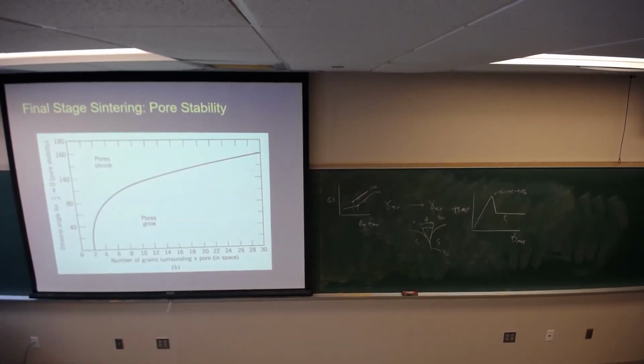One more comment though. Your dihedral angle is fixed because it's dictated by the ratio of gamma SV to gamma SS. So you have a constant dihedral angle, and if on this plot you drew a horizontal line, that would tell you then, based on that dihedral angle, the pore coordination necessary for pores to shrink versus pores to grow. Okay, so as your dihedral angle goes up, the coordination of the pore necessary for the pore to shrink will have more grains around it before and while it shrinks until you get to where the pore wants to grow. Okay, so that's the argument.